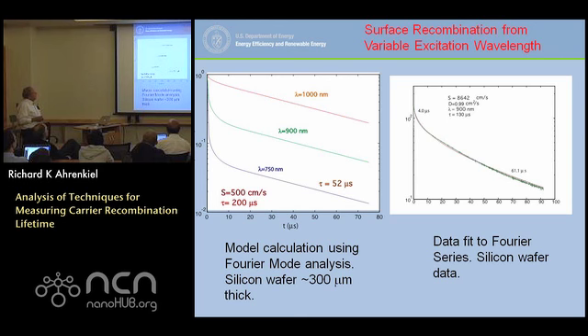Now, we fit the Fourier series analysis, the same one that I think Van Roosbroeck, one of the pioneers, developed that's in the literature, and we fit the Fourier series to the decay curve at 900 nanometers, and now we get an S of 8642, or about 8,600 centimeters per second. So we can fit that. But if S were 0, this would be a straight exponential, and as the wavelength gets shorter, this becomes steeper. So just kind of a ballpark order of, is this a passivated material or not? This works quite well to change the wavelength.